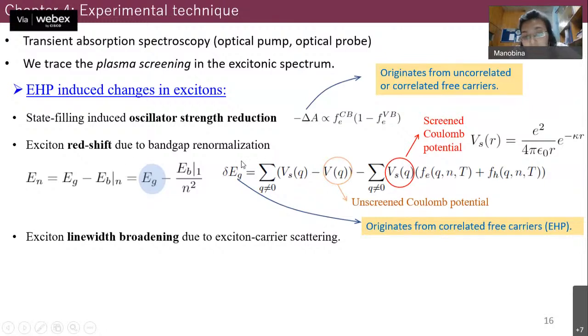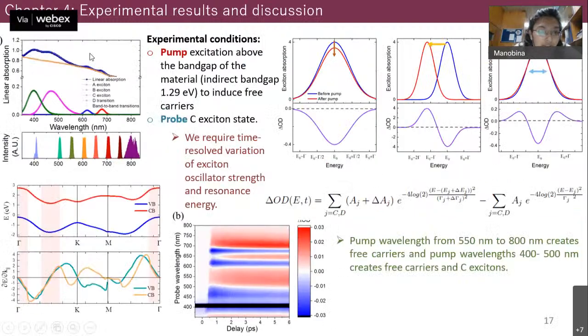Now band gap renormalization comes only when this plasma is formed. So we will not be able to see any redshift if the free carriers are not correlated. So we'll compare these two conditions and distinguish this plasma. So this is again the MoS2 system. So there are 4 excitonic peaks. Here we choose the C exciton, which originates from the parallel valence and conduction bands here.